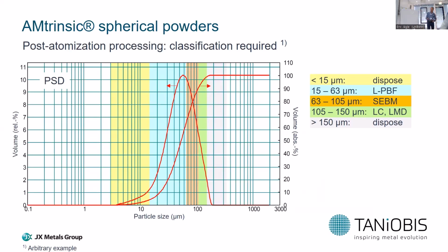The rest, from 10 or 15 to 150, is then sieved into 3 fractions: one which is used in laser powder bed fusion, one which is used in electron beam fusion, so it's 60 to 100, and one which can be used in laser cladding, for example, from 100 to 150. So we have 3 different fractions.